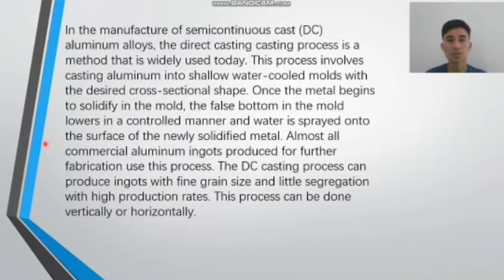In the manufacture of semi-continuous cast or DC aluminum alloys, the direct chill casting process is a method that is widely used today. This process involves casting aluminum into shallow water-cooled molds with the desired cross-sectional shape. Once the metal begins to solidify in the mold, the false bottom in the mold lowers in a controlled manner and water is sprayed onto the surface of the newly solidified metal. Almost all commercial aluminum ingots produced for further fabrication use this process. The DC casting process can produce ingots with fine grain size and little segregation with high production rates. This process can be done vertically or horizontally. Next,